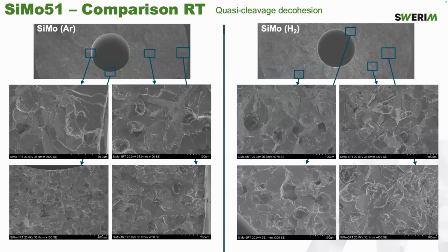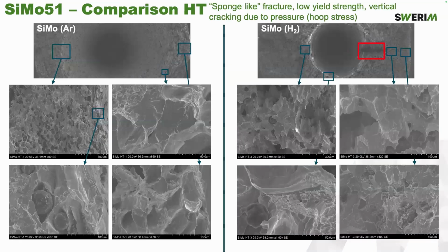SiMo, room temperature, the same here we see on both cases, regardless of the gas, quasi-cleavage decohesion. High temperature, we see a sponge fracture. I don't know how to define this because here we have extremely high temperatures, so we assume that we might have also effect of high temperature hydrogen attack that can result in this.